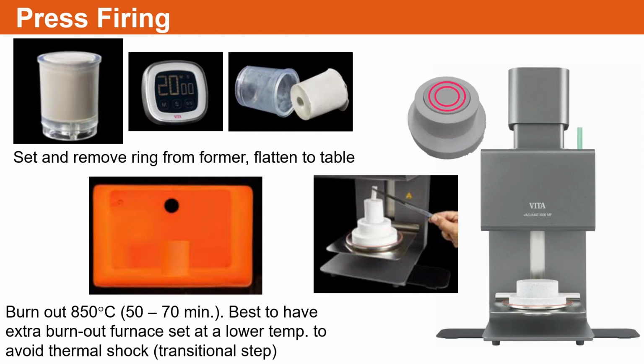And any one of those little micro fractures is a weak point. During the press process, if there's enough pressure, it just basically takes those micro fractures and blows them apart. So it's not the investment, it's not the furnace, it's not the material itself. It's mainly the process that we have to pay attention to.